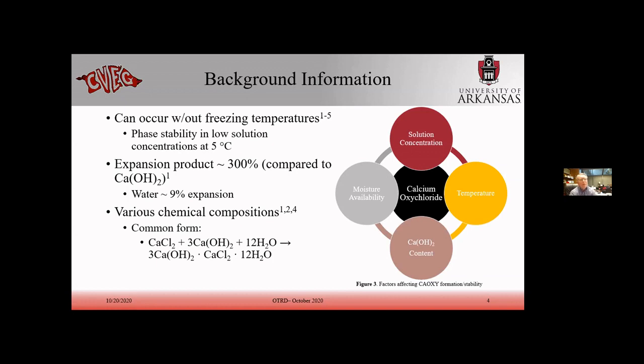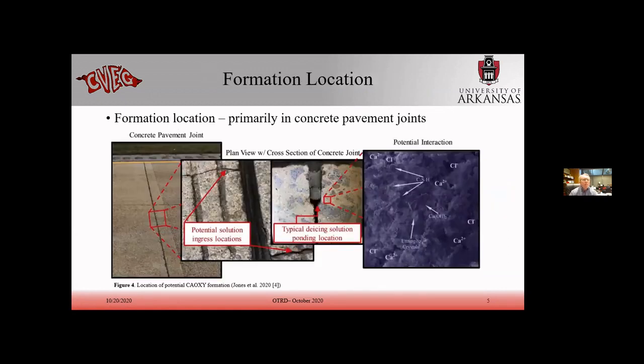The 300% expansion is basically because you're combining your de-icing salts, your calcium chloride, plus your calcium hydroxide and 12 water molecules to give you the calcium oxychloride. So it's a bigger compound. It's significantly larger, and that expansion within hardened concrete can exceed its tensile strength and cause cracking.